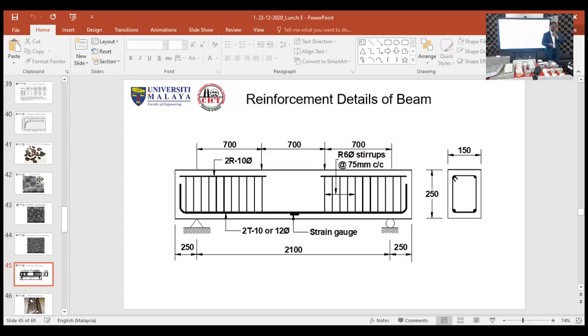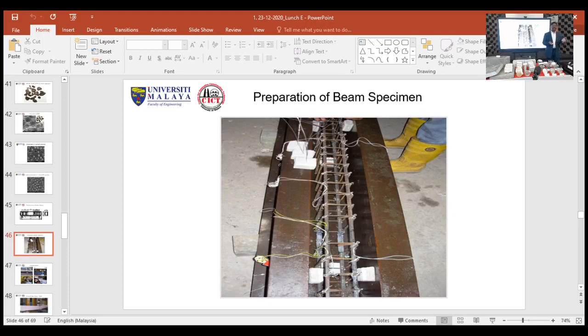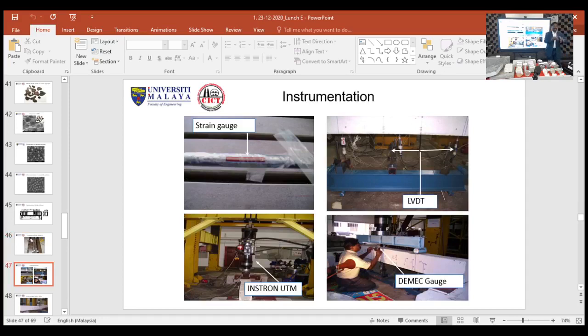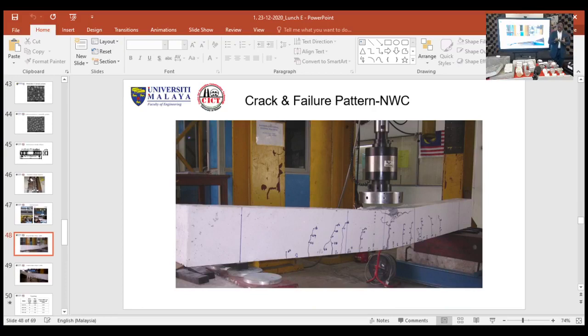What you see is the conventional reinforced concrete beams of 150 by 250 mm size, and we have investigated this with the strain measurements, deformation, deflection measurement, and the load capacity, bending moment capacity. So this is the fabrication of the beam, what you can see there with the strain gauges and with the DEMEC gauges. All these were placed, and LVDT was used to measure the vertical deformation. This is the instrumentation that you see.